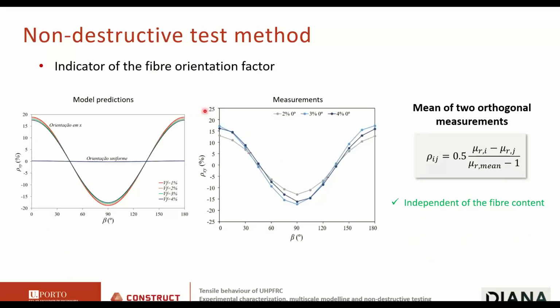What about an indicator of the fiber orientation? We found out that this is a good indicator of the fiber orientation. We take the same two measurements at 90 degrees, but now we use this equation instead. The model says that this is nearly independent of the fiber content. You see the model predictions for many different fiber contents, and it's almost the same curve. And this is what we see actually in the experiments.